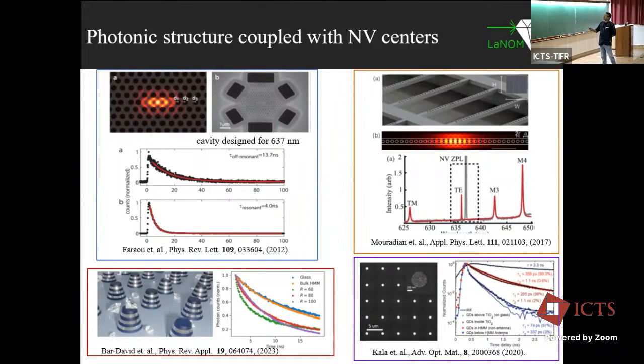And this other work is nanobeam cavities, where you have an array of holes and you try to create an NV center. But you can see here, they try to match the cavity mode very close to 637 nanometers, which is the zero phonon line of the NV center. This is a very recent work. Last week it appeared in Physical Review Applied, where they made a hyperbolic metamaterial and then trapped these NV centers. It's a cartoon picture where they try to show the increase in the sensitivity of magnetometry and other experiments.